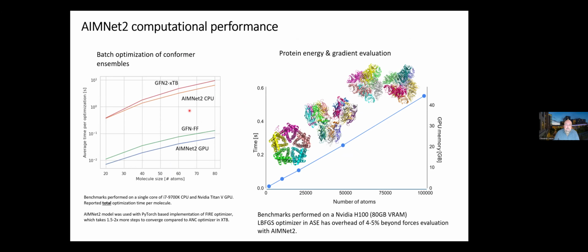Just a little example. AIMNet2 is linear scaling in the regime of larger systems. So for 100,000 atoms, getting energy and forces takes about half a second. So it is slower than traditional force fields, but it is much, much faster than DFT. Here on the left is also a comparison with the popular methods from the Stefan Grimme lab from Bonn, GFN2-xTB and GFN-FF. Again, AIMNet is about 10 times faster, and therefore you can do simulations, for example computing energies of conformers within a few seconds on a GPU.